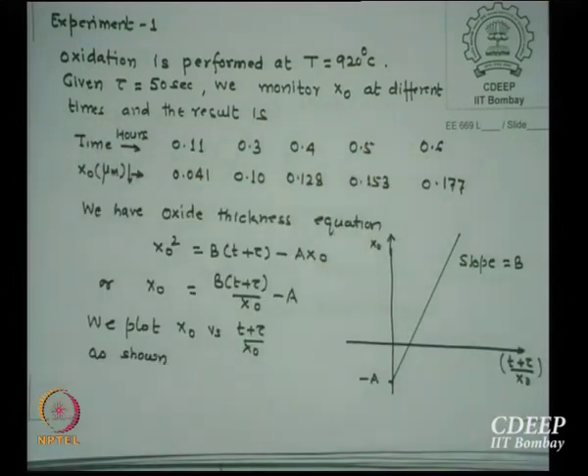And then I figured out later, maybe I don't know whether I have the graph, okay, I'll show you. It shows that it is actually following the physics, that is KS and diffusivity. Whatever their temperature dependence is, the same happens to B and B by A as well. We will see this a little later. So I can monitor B and B by A by actually monitoring the oxide thicknesses at different times of oxidation. Is that point clear?